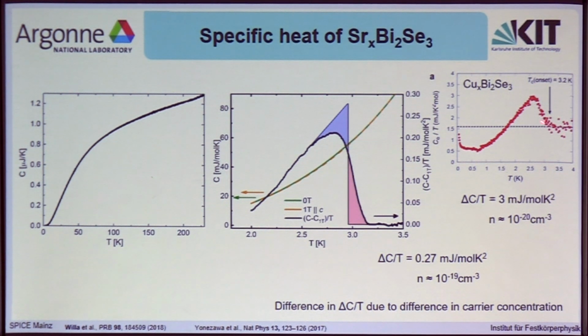It shows a specific heat jump that is about a factor of 10 larger than the one at strontium-doped bismuth selenide. However, also the carrier concentration of this compound is about a factor of 10 larger. So we think this small jump is mostly due to the low carrier concentration in our material. So having measured that jump, of course, we also wanted to see whether we also see this twofold anisotropy